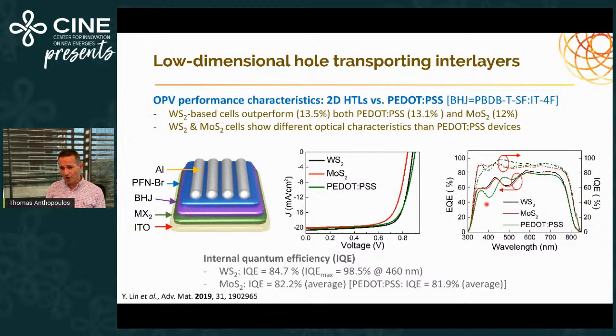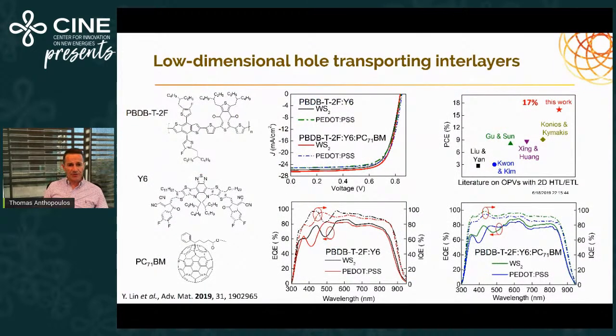The higher current is primarily attributed to a change in the photonic structure of these devices. And of course, when we compare with PEDOT:PSS, we have this reduction of the parasitic absorption that PEDOT:PSS has. Even though it's optimized in terms of thickness, PEDOT:PSS will tend to absorb in the near-IR part of the spectrum, which is very critical. And as you can see here, we also see a change in the way the entire EQE spectrum looks because of the changes in the photonic structure of our device. Essentially, we're removing a thin film and replacing it with an atomically thin layer, which does not have the same optical effect on the photonic structure of this cell. So essentially, this is a summary of the hero devices.